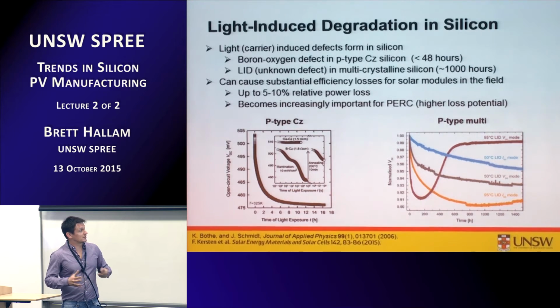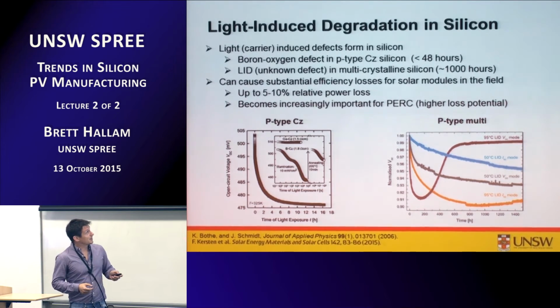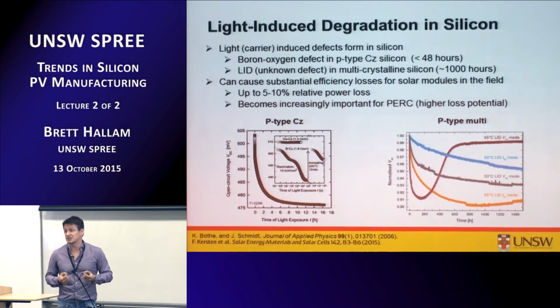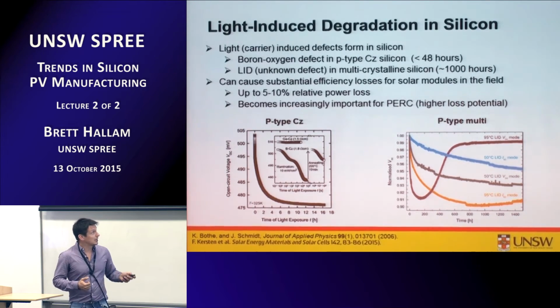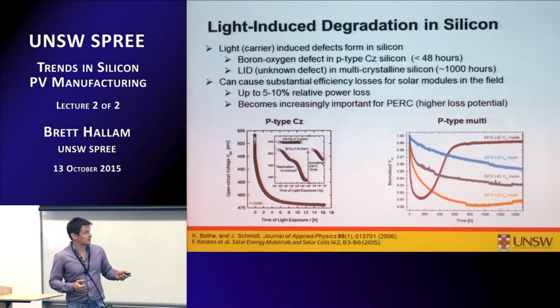So in terms of the mechanisms of these light-induced defects, we've got the boron-oxygen defect, which typically occurs over a time scale of about 48 hours at room temperature to fully form these defects. There's also another defect in multicrystalline silicon that's just become apparent. It's not actually known what this defect is yet. It has a much longer time scale, about 1,000 hours to fully form this defect.